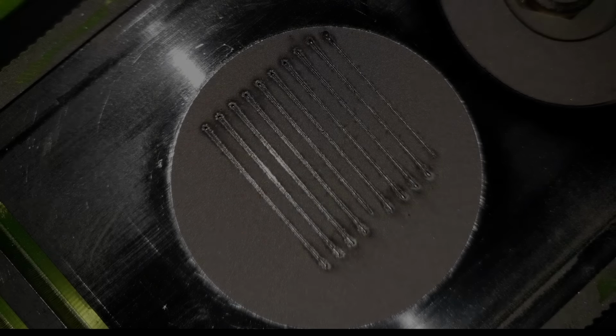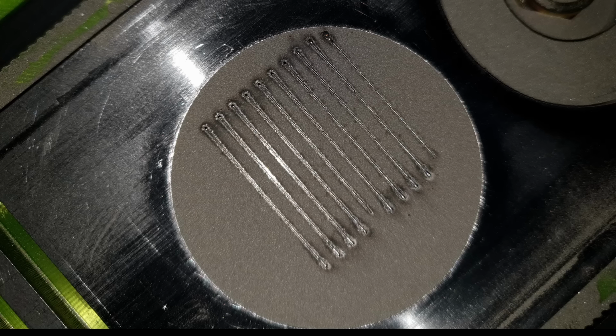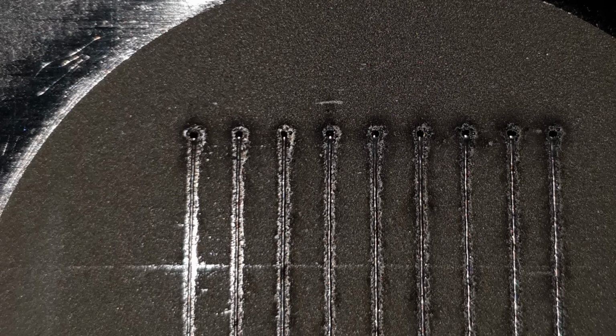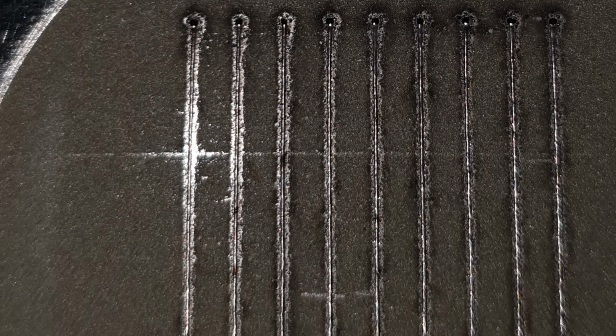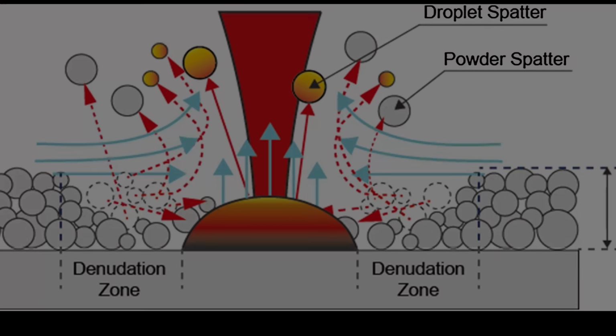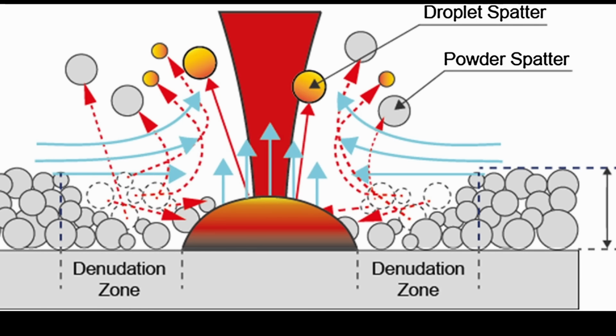So I guess the best place to start is where things left off, and this picture pretty much sums up why I gave up on laser powder bed fusion the first time around. I was under the impression that the vacancy in powder running alongside the deposited tracks was due to recoil pressure. This is a pretty well known phenomenon, often resulting in denudation, where the recoil pressure creates negative pressure on either side of the melt pool, drawing the surrounding powder through the plasma stream.